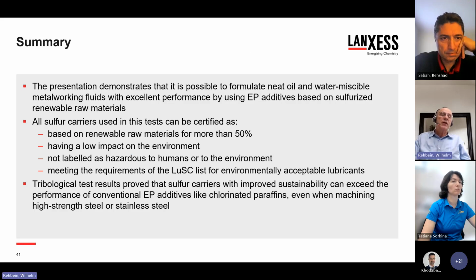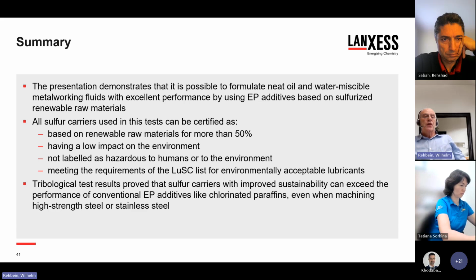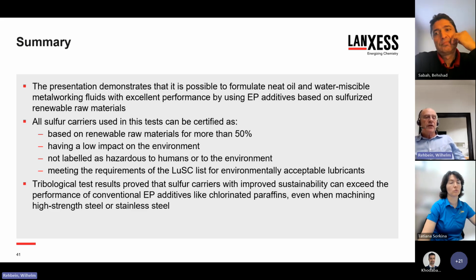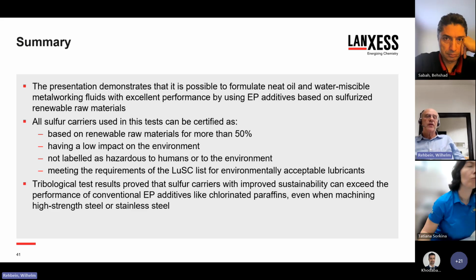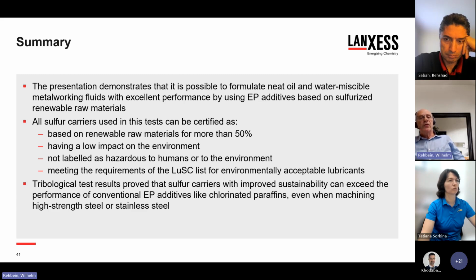So finally, we can conclude that this presentation demonstrates that it is possible to formulate neat oil and also water-miscible emulsifiable metalworking fluids with excellent performance by using EP additives based on sulfurized renewable raw materials like vegetable oils or vegetable oil methyl esters. All the sulfur carriers that I showed in this test can be certified as based on renewable raw materials for more than 50%. The remaining percentage is just sulfur. They have a quite low impact on the environment.